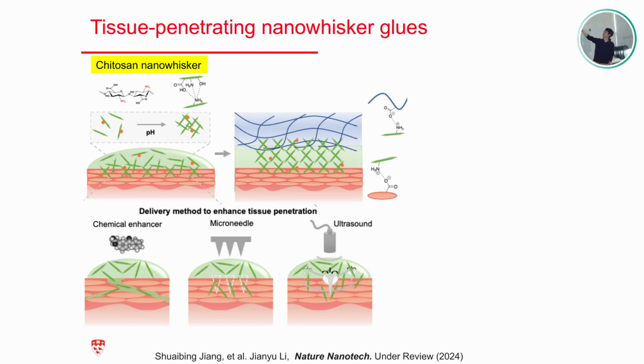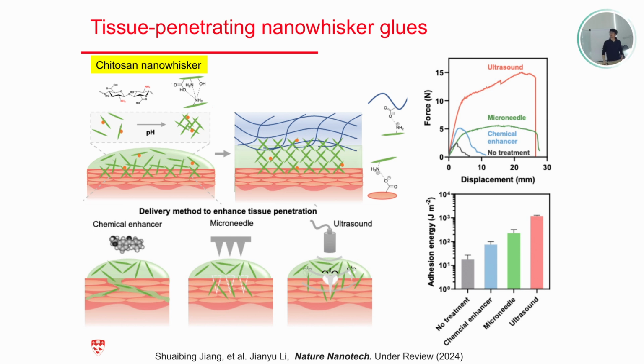So this nanoparticle also has abundant functional groups such as amine groups as well as carboxylic groups, residues of the chemical processing treatment we have done to originate the chitin nanocrystal. So with this nanoparticle, it has high aspect ratio. It can really kind of entangle together and assemble to form this kind of very rigid condensed cluster on the interface between the hydrogel and the tissue. So with all of that, we first tested the adhesion performance.